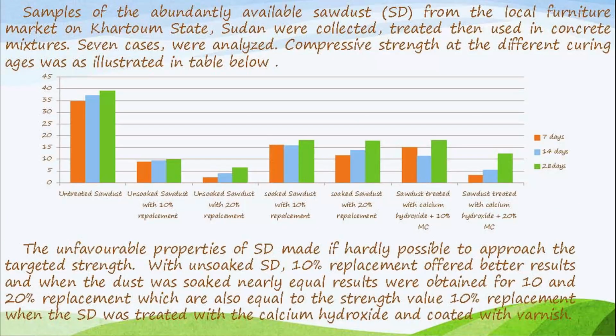The sawdust sample came from the local furniture market in Khartoum state. Then we collected the treated sawdust and used it in the concrete mix for 7 cases. We conducted the compressive strength test for the 7 trials. We have some positive results from the treatment for using sawdust as replacement for fine aggregate.